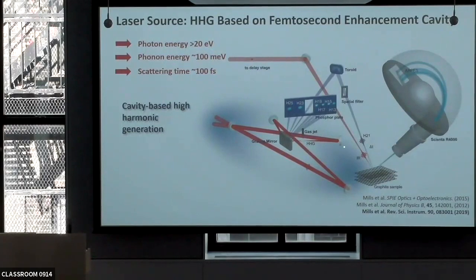So here the idea was to create a cavity, and this is David Jones and our Mills group. Create a cavity which you pump with an oscillator, you store energy in that cavity, and you still have a gas jet, but now you're working with a very high repetition rate and very low peak powers, therefore you can control the temporal energy profile very well. You're going to generate very few high energy or UV photons, but because the repetition rate is so high, you have many of them per second, so you can do the experiment. In fact, you generate an array of harmonics, and you use an image that has been measured in the chamber, and you select one, which is then sent onto the sample. At the same time, you come in with your pump pulse, and you can do the experiment.